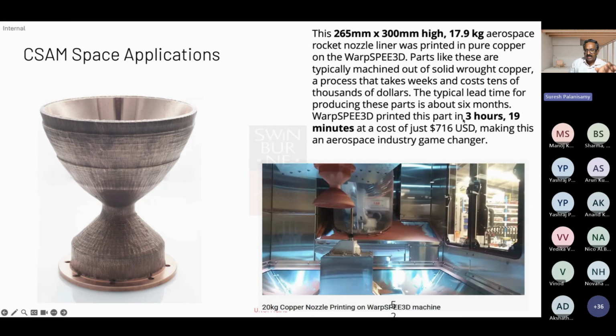So this is one of the key comparisons, I would say. In one of the graphs I showed you earlier, compared to the powder bed process or EBM process, the speed is high, really fast. No way this can be printed in 3 hours. It will take days to print in a powder bed process. DED might take a little less time compared to the powder bed, but still it won't be fast enough compared to the cold spray process. The only thing far more advanced speed-wise is, as I told you, the additive friction stir deposition process. That's far faster than this one because the speed is very quick in that case.